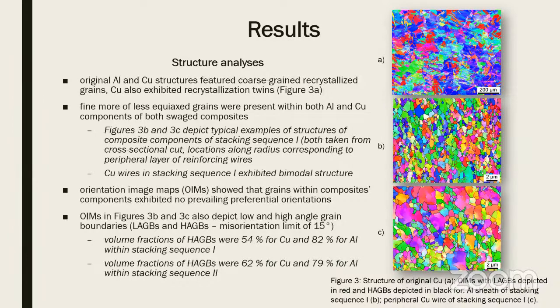All these orientation image maps, which also depict the orientations of the grains according to the colors, show that there were no preferential colors prevailing in the structures, which means that there was no prevailing preferential texture of some very high intensity.